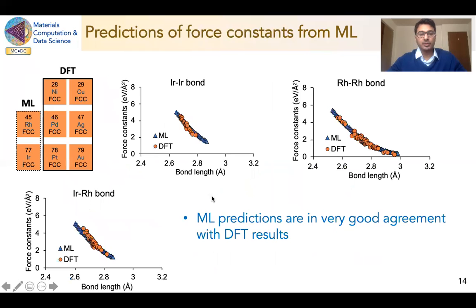In this slide, the force constants versus bond length relationship for iridium-iridium, rhodium-rhodium, and iridium-rhodium bond is shown. Now, the important point to note here is the model is trained on these 6 elements, meaning these bonds are not present in the training data. And you can see that the predictions are good. Orange data points are from the DFT and blue triangles are from the machine learning model. And you can see that there is a very good agreement between DFT and machine learning. And the model also captures the shape of the curve very nicely.